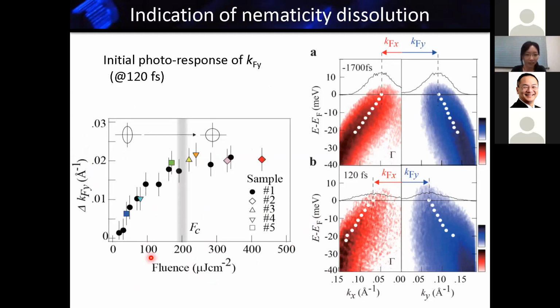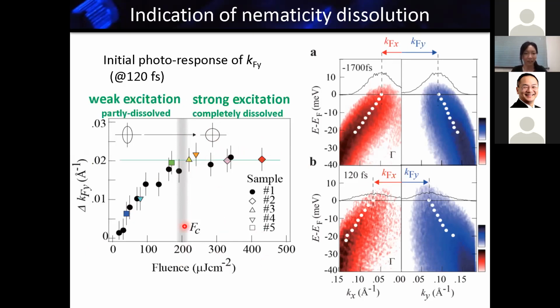And this is the change of the Fermi momentum as a function of the pump fluence. When you excite the system stronger and stronger, this change of the Fermi momentum increases like this. But at some point, it saturates. It means that the Fermi surface just after pumping becomes completely circular in this region. This is a weak excitation regime, which means the Fermi surface only partly becomes circular. But in this strong excitation regime, the Fermi surface completely becomes circular and four-fold symmetric.